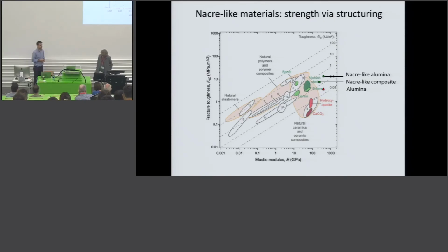Right. So the spacing will affect mostly the volume fraction of your platelets. That's the largest effect that we see. We can take this part, which is still not heat treated like this one, and by changing the pressure that you apply during this high temperature, high pressure, you can basically manipulate the volume fraction and the distance between the platelets. In terms of volume fractions, you would change it from 30 to 40 all the way up to 95% of your platelets. And we tend to see a linear relation with the volume fraction, and that is in agreement with what one would expect from composite theory.